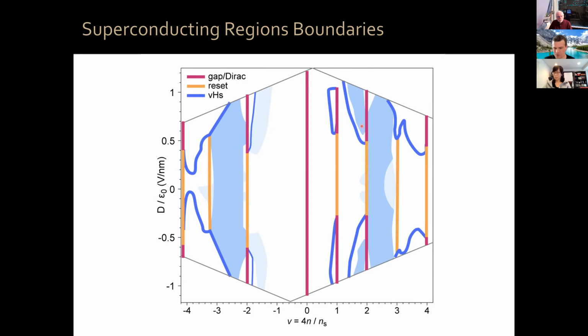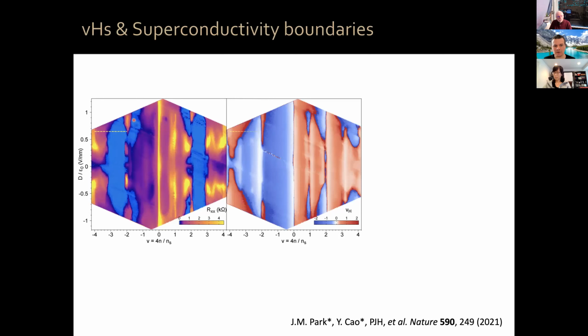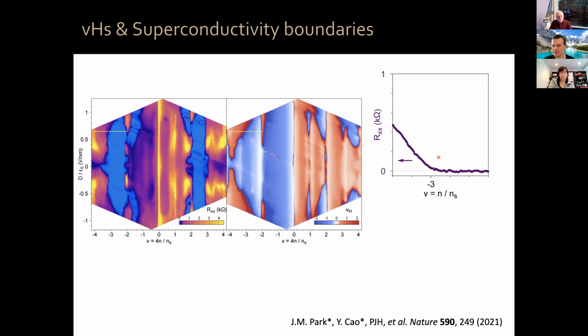Okay, so let's look a little bit more in detail at this. Let's look at this diagram and let's look at the properties along this dashed line, which intersects a Van Hove singularity here, as you can see. Okay, so if we measure the resistivity, it's of course 0 in the superconducting state, and then it becomes finite when you come out of the superconducting state. Okay, now we can measure the critical temperature, the BKT transition, as a function of filling factor along the same trace, and it's finite, and of course it's 0 the moment the system stops being superconducting.